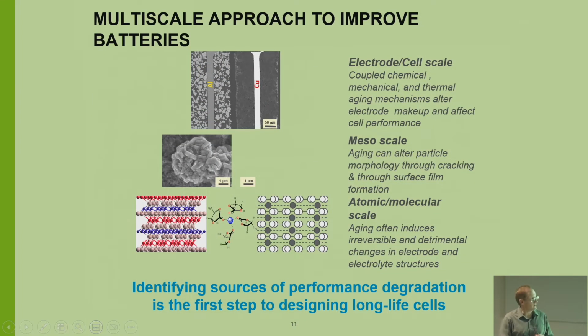Here's where all the science and engineering comes in. So you can really think of the battery research in three general areas. You have the atomic molecular scale. So that's where people are working on the crystal structure, trying to create different additives in that crystal structure. Do we put in nickel instead of the cobalt, manganese instead of the cobalt, throw some aluminum in there, just to see what effect that has at the crystal structure scale.